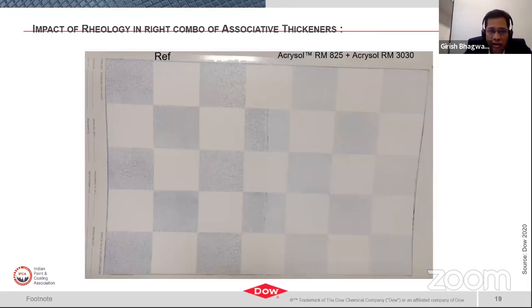Similarly for associative thickener, when you see on the left hand side, here we have put multiple, 2 or 3 coats perhaps. There is sort of the underneath black surface which is visible. The paint has not flowed to the extent that it should have. So the film is not uniform on the left hand side. On the right hand side, when you use the right choice of associative thickeners, which has a perfect balance of low and high shear viscosity, eventually it will translate into a more uniform film, which will hide the substrate and also give you a perfect feel that it is not having any kind of issues with respect to appearance. So the rheology profile, when you saw, you needed low shear, you needed mid shear, you needed high shear. How does it translate eventually into